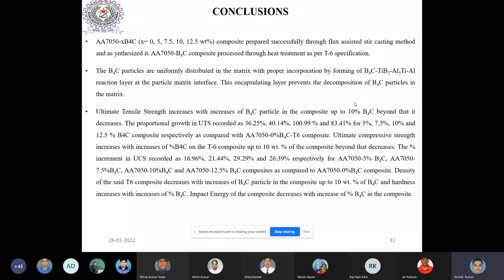We have successfully prepared and synthesized a composite through the flux-assisted casting method, and this composite went through a heat treatment process. Then we are able to make a uniform distribution of the matrix with proper incorporation by forming B4C, TiB2, Al3Ti and aluminum, that is a quaternary layer. If we form it, then we can have a good load-bearing composite, and as a consequence we have got very good mechanical properties as well.